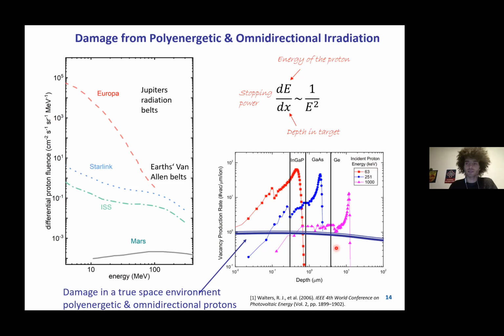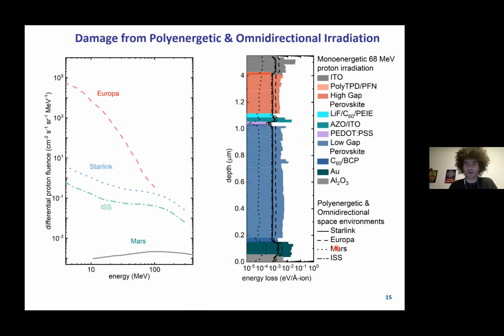So I've been trying to simulate this for a perovskite tandem, and I'm now showing results here. What I'm plotting is the energy lost by the protons in the individual layers. The red here is the high gap top cell, and the blue is the low gap perovskite subcell. And you can see quite nicely that the damage is rather homogeneous for a variety of different orbits.